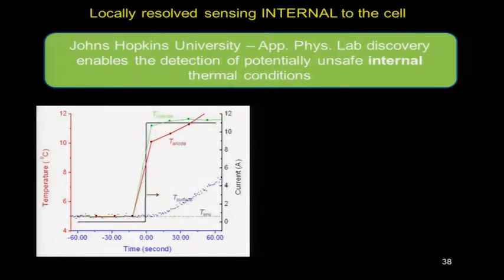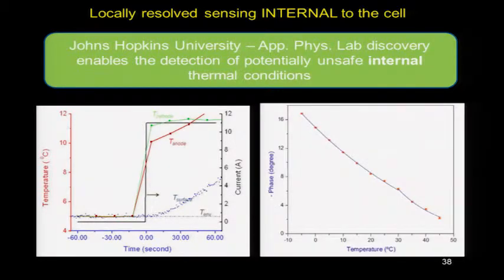This is the temperature on the outside. The dotted line is the temperature of the outside of the battery pack. And this is the temperature of the anode and cathode. You can actually measure the temperature by putting a fairly low frequency test signal into the battery across the plus and minus. And the change in the phase shift of the frequency coming back out tells you the temperature of the battery, and it's surprisingly consistent with a given battery manufacturer, across battery to battery to battery. And again, because it's just low frequency, like a few hundred hertz, it's very inexpensive electronics, and it tells you what the temperature is internally in the battery. So it would be a great help.